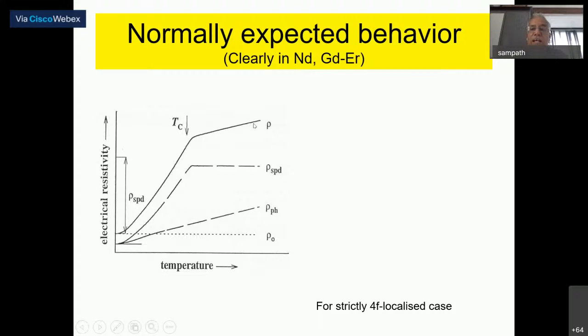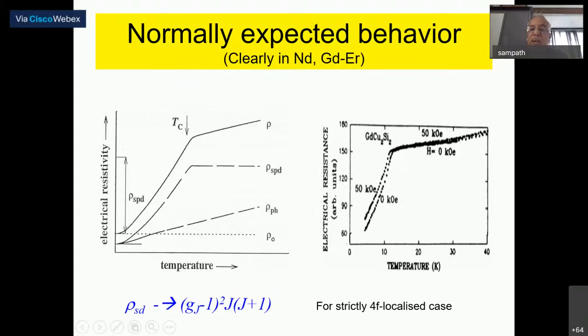So if you apply a magnetic field and measure magnetoresistance, this number is expected to scale with the de Gennes factor I already mentioned. This is for a strictly localized case. Therefore, when you apply a magnetic field and measure magnetoresistance, you will find in the paramagnetic state virtually very little effect on the electrical transport. Therefore, magnetoresistance is much, much less than 1.